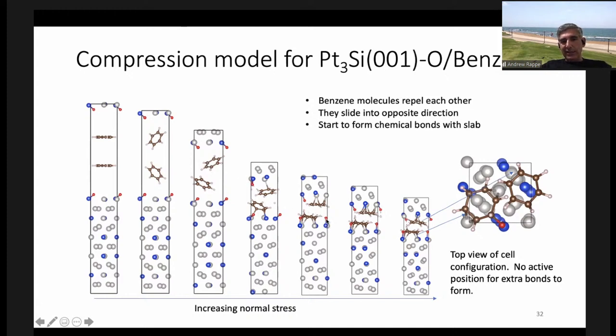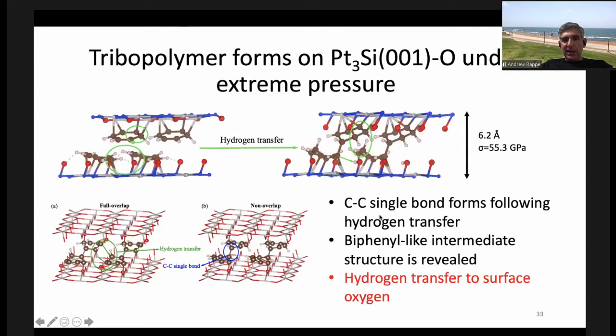And you can see that there is some interaction between these molecules. And there is hydrogen transfer to the surface, but it requires 55 GPa of stress for that to happen. And eventually, again, the same reaction happens. So you get this biphenyl intermediate with the carbon-carbon bond following the hydrogen transfer.